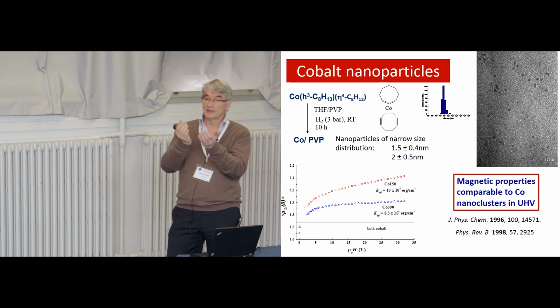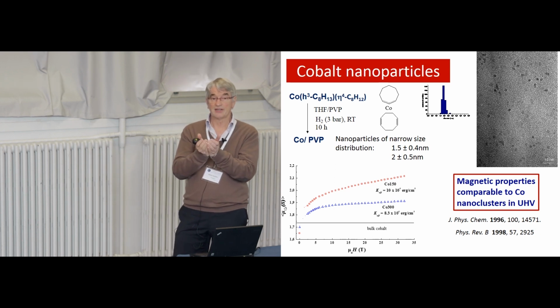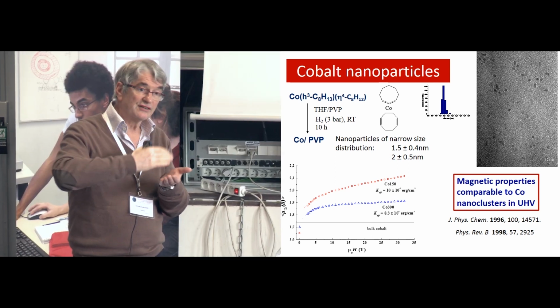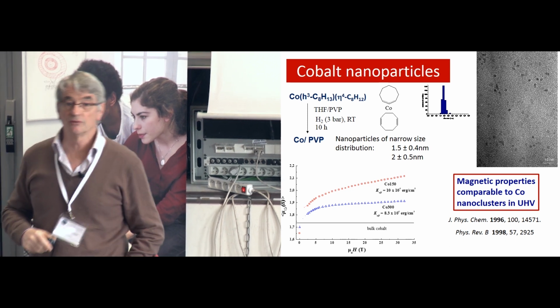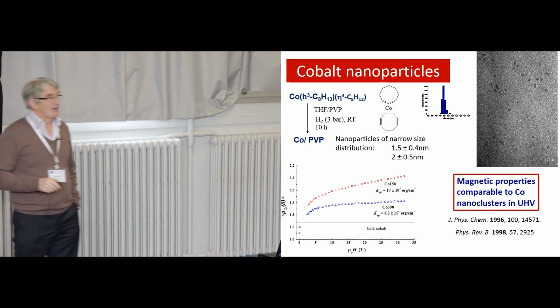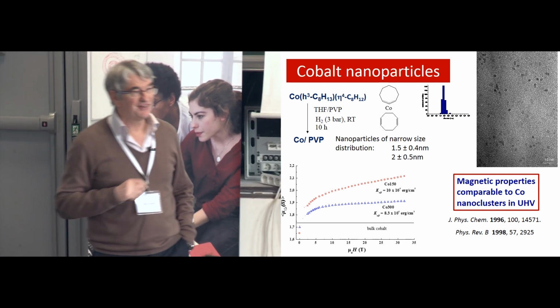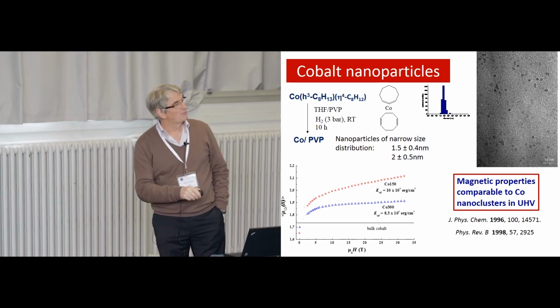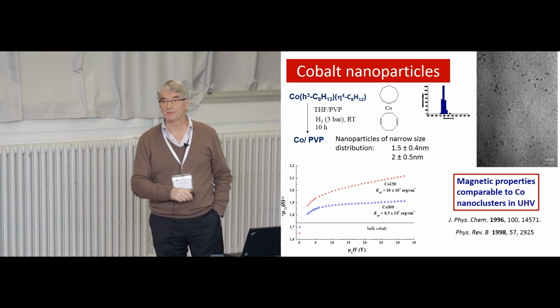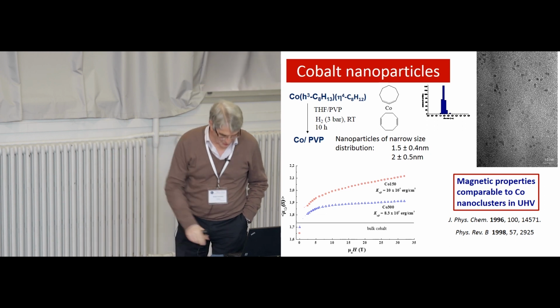And that had only been seen in ultra-high vacuum. So the nanoparticles prepared by organometallic chemistry can compete, for physical properties, with nanoparticles prepared in UHV. It has been very hard to publish that, and the physicists would not believe it, but finally it was published, and this is my most cited paper.